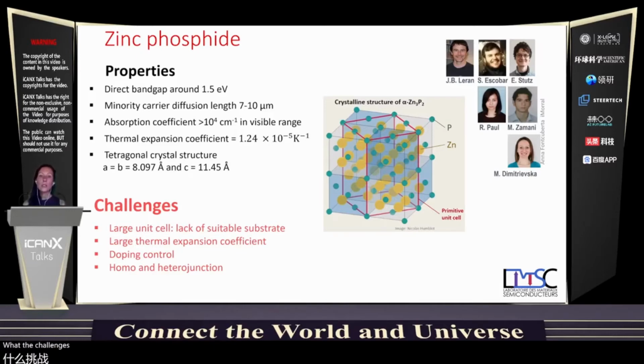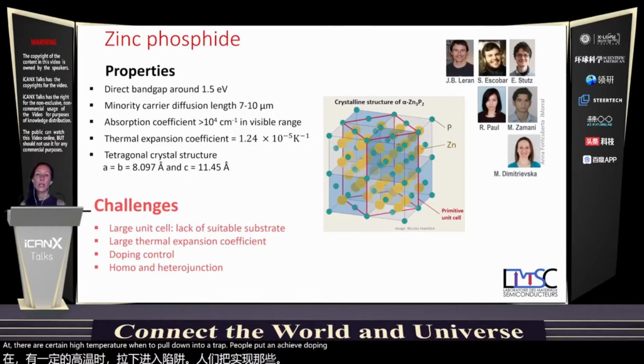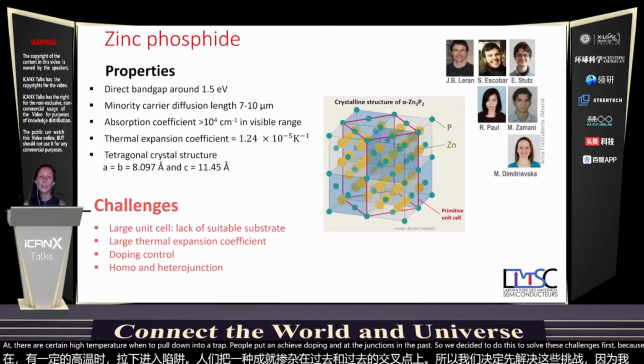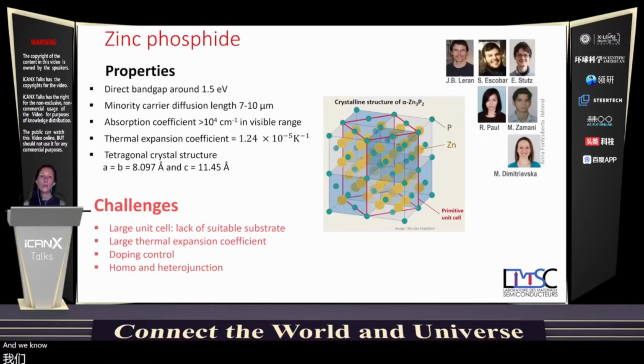The challenges in this material, and why people didn't try it before, are that there is no substrate to grow it on, and it has a very large thermal expansion coefficient, which means even if you can grow it on a substrate at a certain high temperature, when you cool down, it will crack. People couldn't achieve doping and heterojunctions in the past. So we decided to solve these challenges first, because material science has evolved since people tried this before. And we know the advantage of nanostructures, so we'd like to utilize the advantage of nanostructures to work